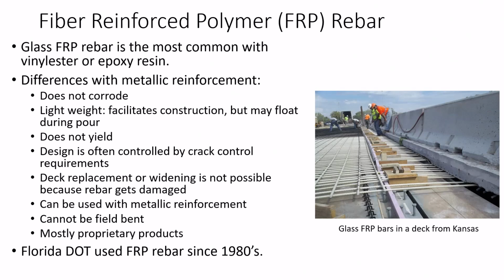cover. But there was some discussion about how the FRP grid may float during the concrete pours if you don't secure it well in place. And so because of that, some DOTs were worried about that floating issue, and they still went with the larger cover. So these bars do not yield, so essentially they're elastic and then they fracture.